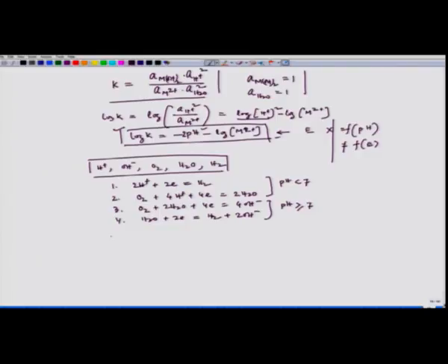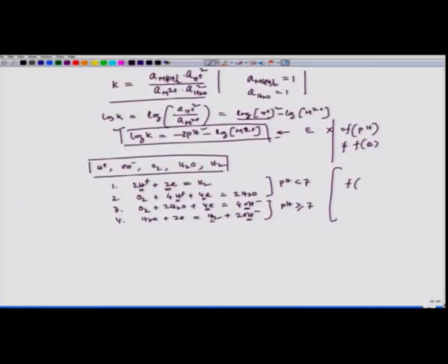Now, in all 4 reactions you see that electrons are involved, and we have the H plus ion present in 2 cases and the OH minus ion present in the other 2. Whether we have H plus or OH minus, we can express the Nernst equation in terms of potential as well as pH. So, all 4 reactions are functions of potential and pH. In the OH minus cases it is a function of pOH, which can be written in the form of pH.